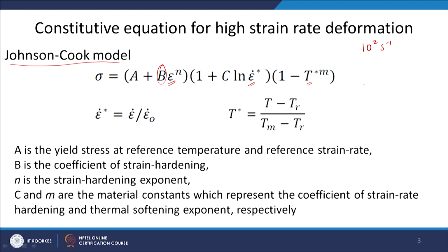from your thermodynamics you must be knowing, that is what we call as adiabatic heating. That means, adiabatic temperature rise, because you are not allowing heat to dissipate. So, you have created an adiabatic condition. So, at very high strain rate, when you are deforming, because you are not allowing heat to dissipate, temperature will rise above the temperature of deformation.